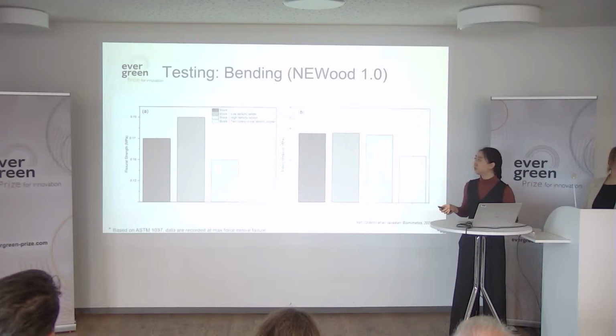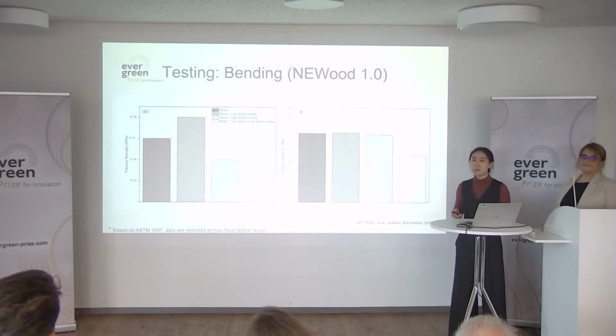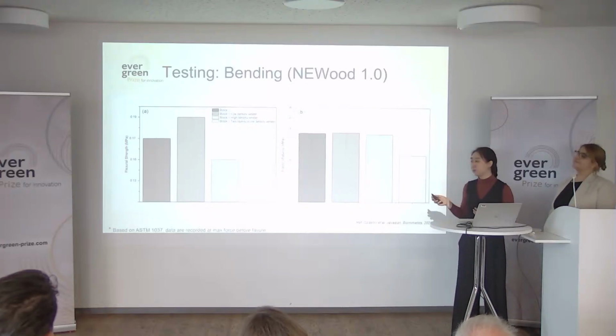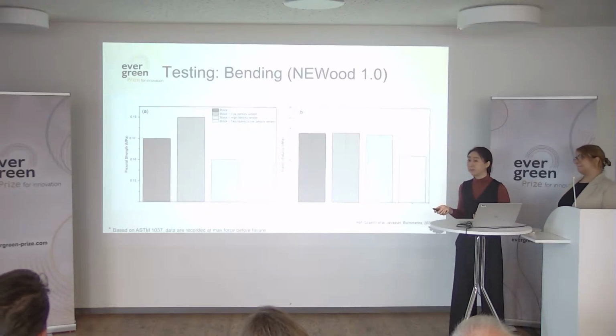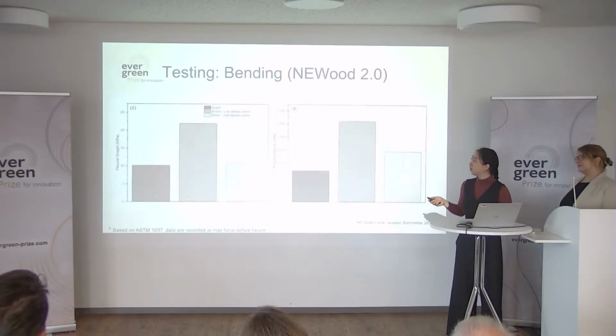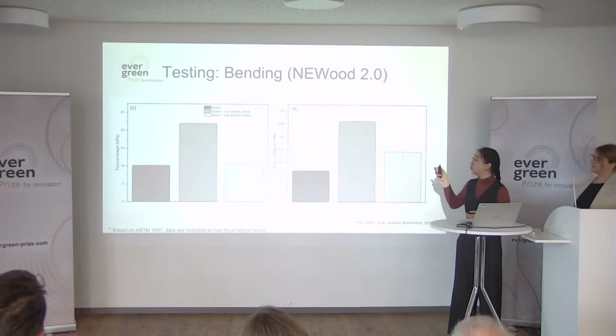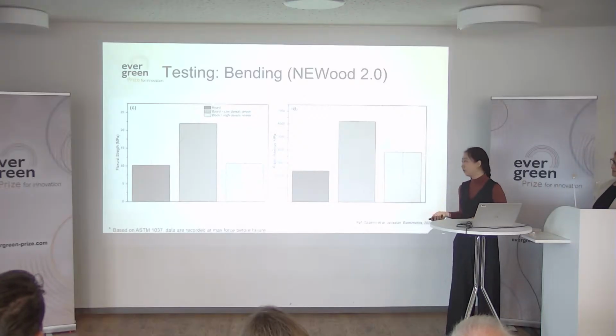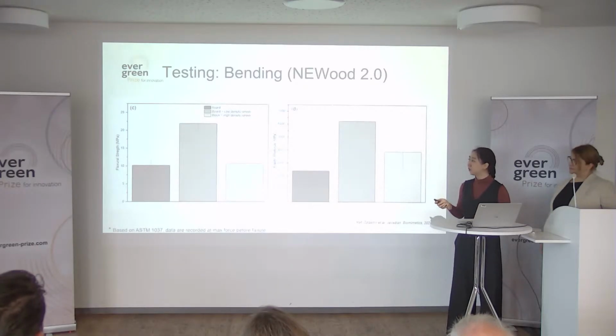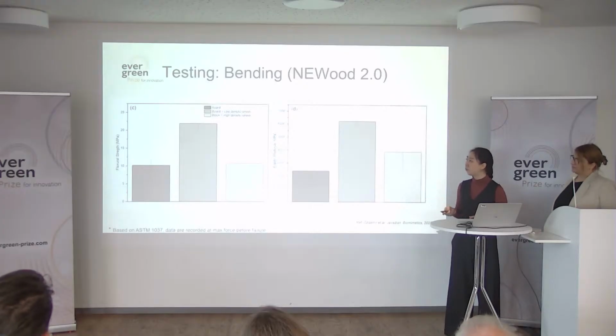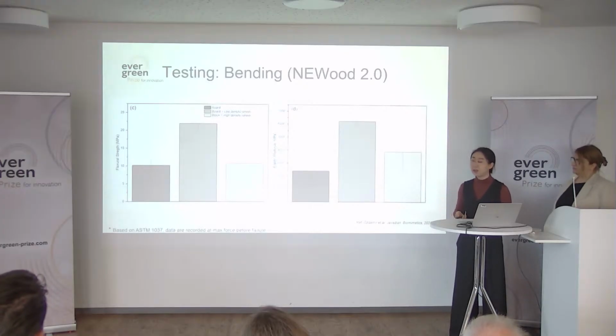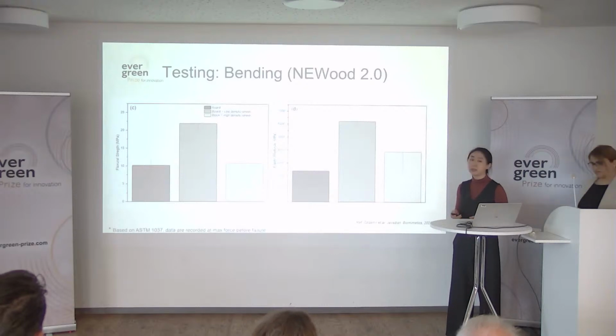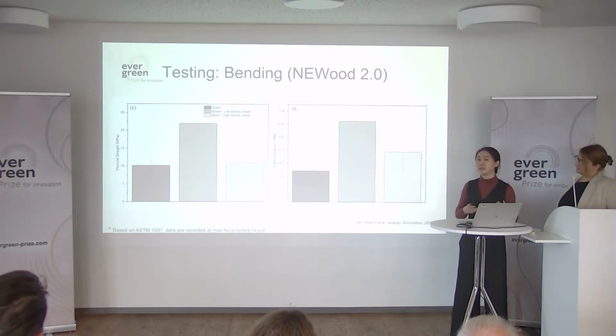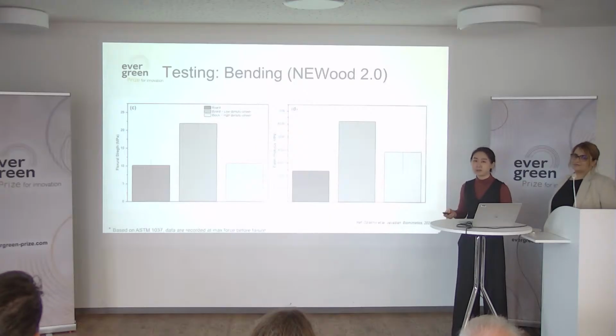We have also conducted some bending tests on NEWood 1, and what we found was that we were able to add wood fibers into the material to reinforce our mycelium composite. That actually helps to make the mycelium composites stronger. The wood veneers will also help to reinforce NEWood 2, which is the denser version of our material. And with this, we were able to achieve bending strength of more than 20 megapascals, and the material has elastic modulus of more than 6 gigapascals. So this actually draws quite close to the commercial products now available on the market.